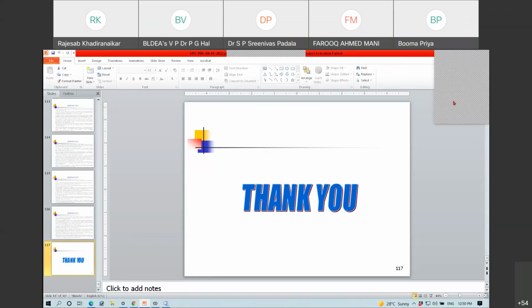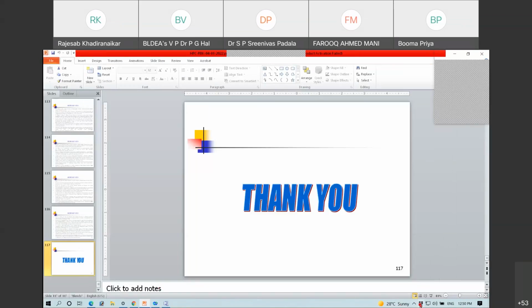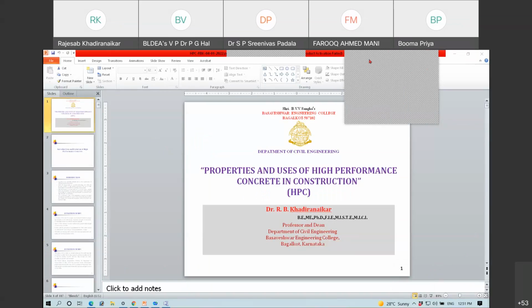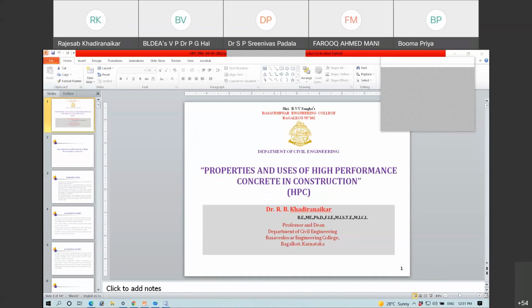What should be the optimum size of aggregate for high performance concrete? Well, there is no single size for all grades. It depends on what level of strength you are going in for. Say if you are going for 60 MPa, you can go for 20 mm without any hesitation. And if you want an M100, for example, 20 mm may not be useful. You have to go for 12 mm. More than 100 MPa, in that case, you have to restrict yourself to 12 mm or 10 mm downsize. That will be better, more than 100. So it depends on what is the range of strength that you are targeting. So higher the strength, smaller should be the size. There is nothing like optimum.